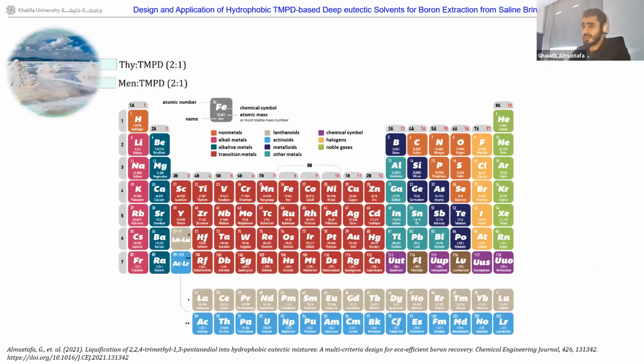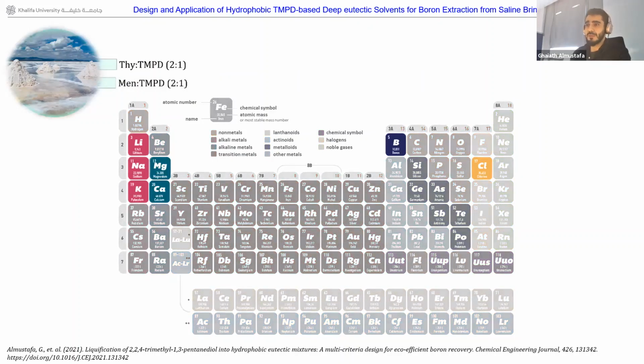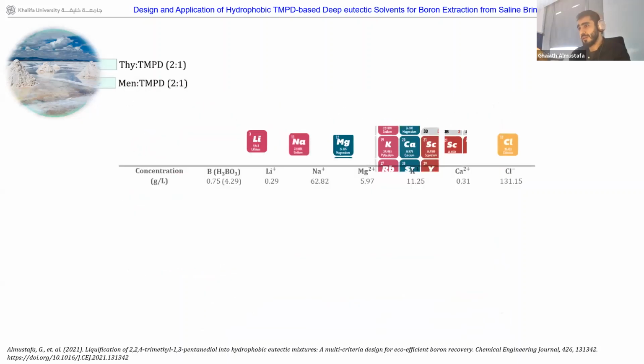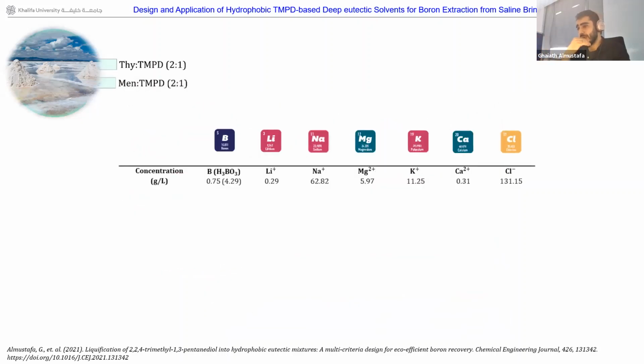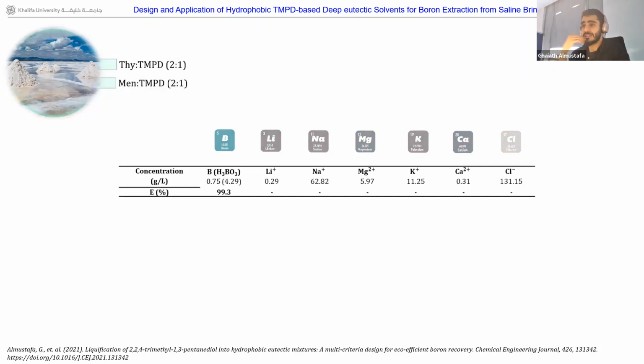And you can see right away the saline brine is not an easy matrix. It contains multiple components: lithium, sodium, magnesium, potassium, calcium, and so on and so forth. So we prepared a surrogate of that solution and we tested it for boron extraction under these extreme conditions. And apparently we have a very selective extraction process with an even higher extraction efficiency of 99%, with no extraction of the other components. And that was kind of expected because you are expecting TMPD to complex with boron through the complexation of the 6-member rings that I showed earlier, and not with the other ions.